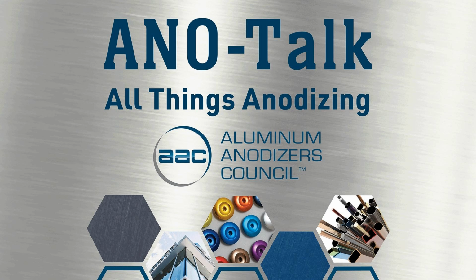Does that mean that for hard anodizing, pulse would actually save you more energy than for type 2? See, that is what I had hoped. Okay, because that would make sense based on what you're saying. Yeah, and it really does make sense to talk about energy in anodizing. If you're only talking about energy from your rectifier, you have to talk about energy from your cooling system also. And when you do hard anodizing, you have to cool your solution down to around 0 Celsius. Or 32 Fahrenheit for the American listeners.